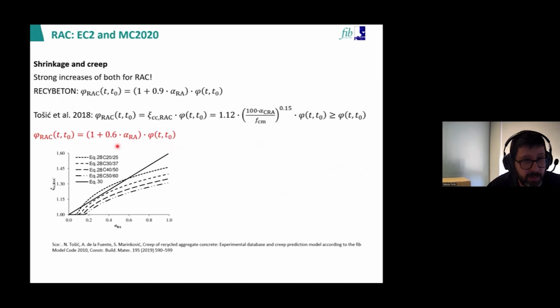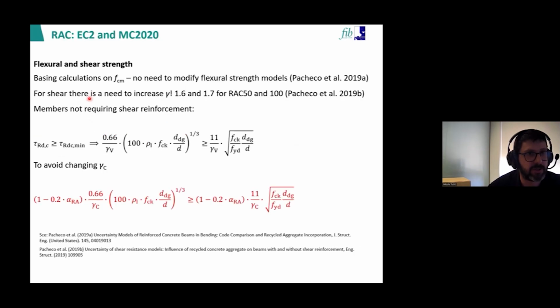Very similar for creep. The only thing is that it's slightly lower, so it's 1 plus 0.6. So it's a 60% increase of the creep coefficient, which you calculate as if it were natural aggregate concrete. Again, everything is in the background documents, comparing different meta-analyses that analyzed a lot of experimental results.